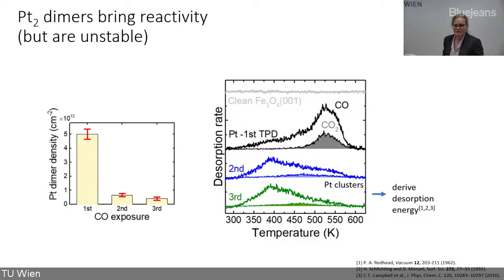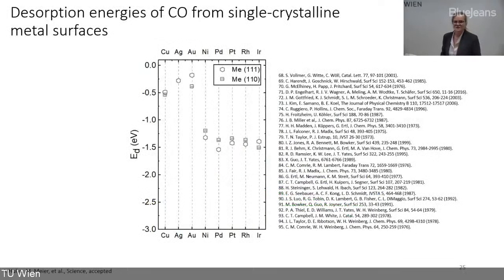There are more or less sophisticated ways to do that, and people have dealt with this for a long time. In fact, people have studied CO desorption on metal single crystalline surfaces for a very long time. This is a list of papers we looked through, part of the reference list of a paper we just got accepted. We looked at different elements from copper, silver, gold across the periodic table to iridium, metal 111 and metal 110 single crystals, and what people reported as desorption energy. In this list are some of the heroes and big giants of surface science. It turns out people have dealt with this for a very long time in great detail.